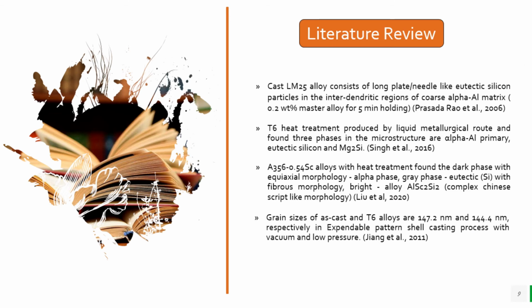Okay, this is a research journal for this study. Based on Prasada Rao in their study, they found that the cast LM25 alloy consists of long plate and needle-like eutectic silicon particles in the interdendritic region of coarse alpha aluminum matrix with 0.2% of master alloy with 5-minute holding.